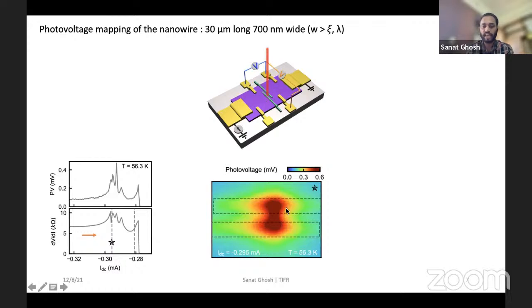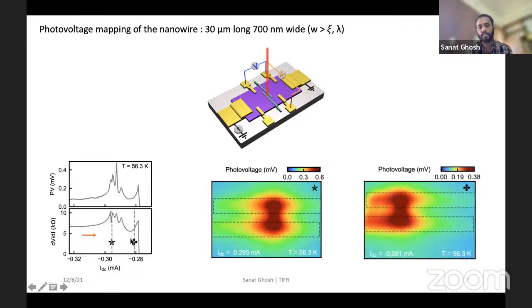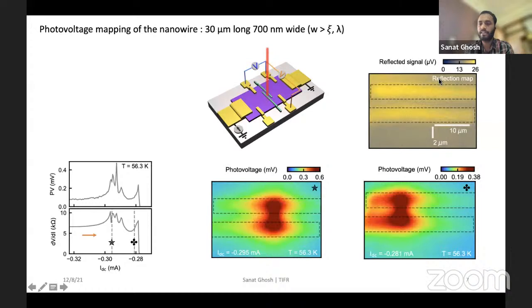And what we see is that there is a maximum photovoltage at the middle of the nanowire at this biasing current. And when we change the biasing current to a different value, this photovoltage maximum point seems to move along the nanowire. And for one-to-one correspondence of this mapping, we simultaneously map out the reflection image from the device. The dotted box that you see is the chromium line boundary, and the gap between the two boxes is the nanowire region. So the summary till here is that the multiple peaks we see in the DVDI data seem to suggest that there are phase slip lines along the nanowire which move as you change the biasing current.